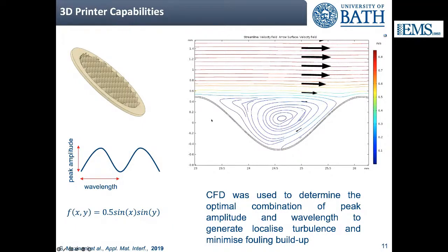So what we did is we started with computational fluid dynamics, thinking of a double sinusoidal structure like the images you see in the top left. What you see on the right here is the streamlines from CFD. Far away from the membrane, there's no distortion, you have laminar flow. When you get towards the surface of the membrane, which is this structure here, you can see that you start having some distortion, in particular in the valley of the 3D printed membrane, you have the formation of vortices.